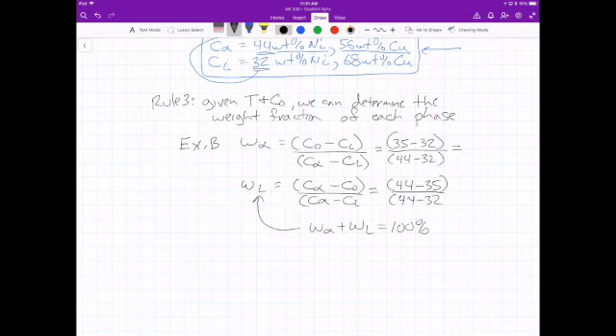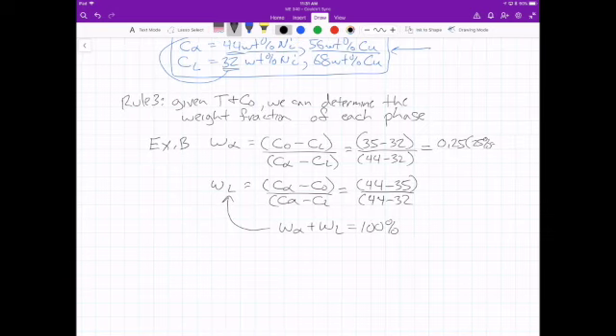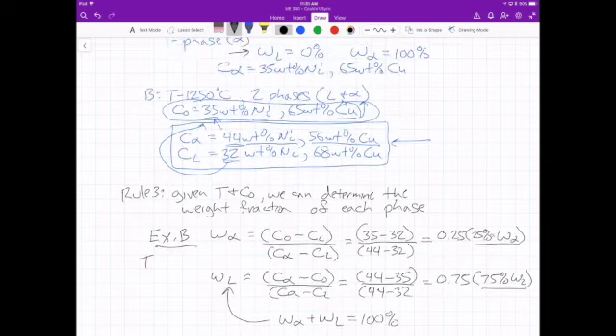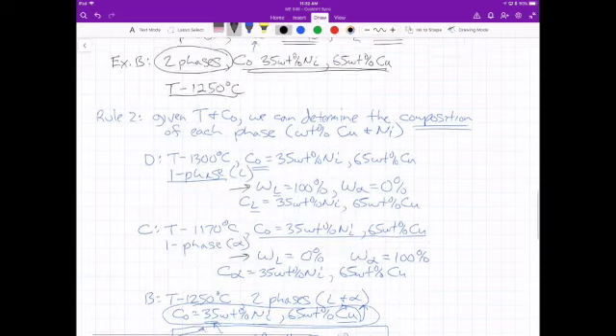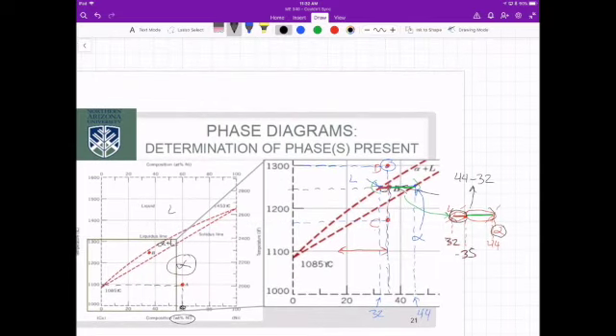Okay. Well, let's calculate these out. This one up here, I get 0.25, which is 25% weight fraction of alpha. This one I get obviously 0.75 or 75% weight fraction liquid. Okay. So at this given point, point B, which was at a temperature, what was it, 1250 degrees, and initial concentration of 35 weight percent nickel. You see that this length of line versus this one, the green line is 3 times longer, and it's opposite to the liquid line, which means it's the weight fraction of liquid. So the amount of liquid is 3 times more than the amount of solid.